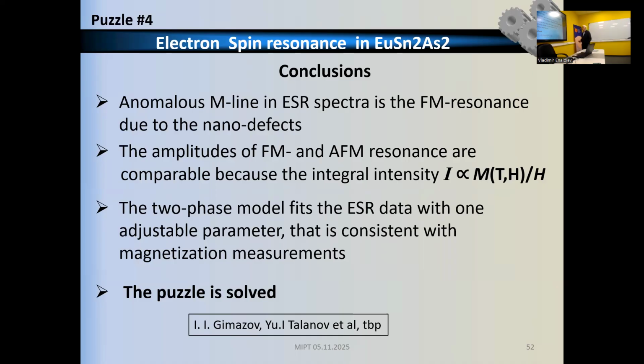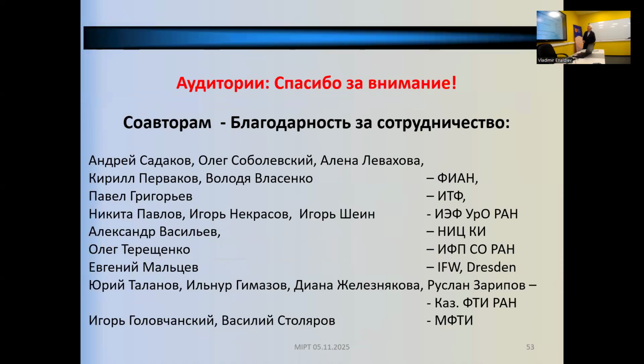And I conclude that the two-phase model fits the spin resonance data. You cannot say this is ferromagnetic or antiferromagnetic because they're both in the same bottle, you have two effects. And more or less it's consistent when you use the adjustable parameter that is consistent with the magnetization measurement for the defect field. So we think that this puzzle is solved.